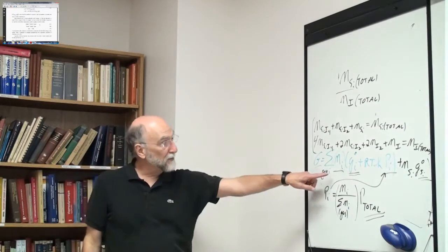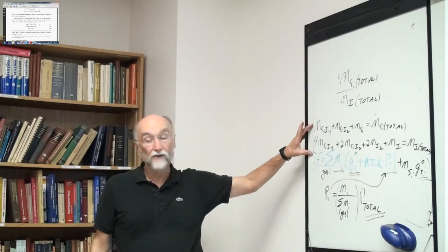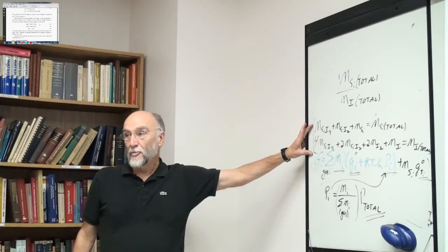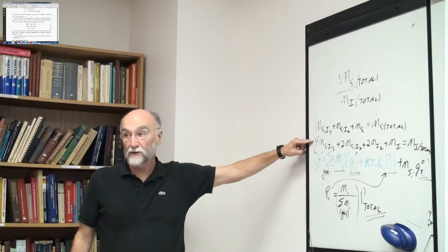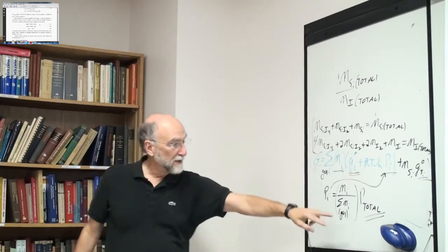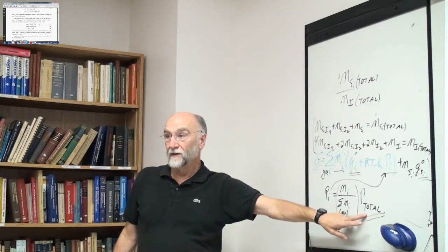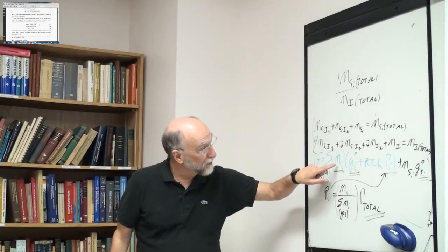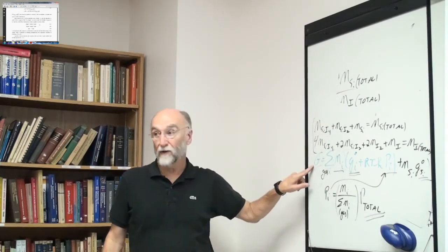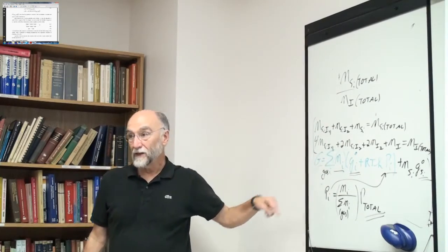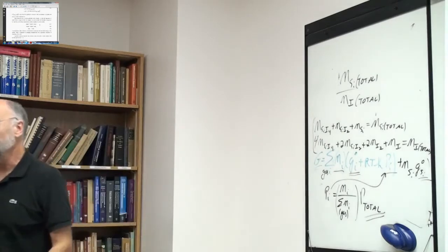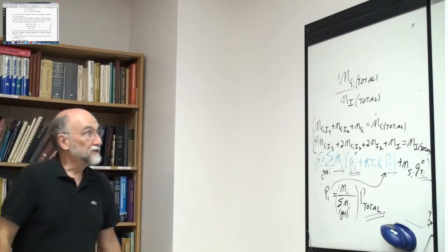So I have to minimize the Gibbs energy under what are called constraints. My constraints would be mass balance constraints for a closed system, and a total pressure constraint, and then I try to find the number of moles Ni of every species that minimizes the Gibbs energy. That's what the Gibbs energy minimization program does. You can set other constraints.